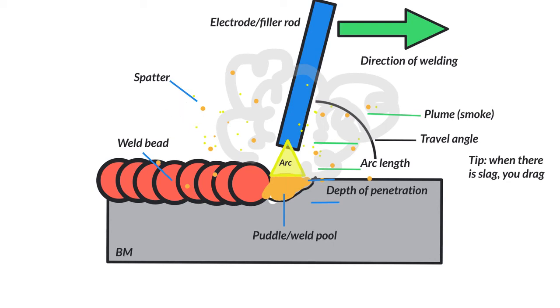We usually get spatter in about all major processes except for TIG. If you've got excessive spatter, we've got an issue — let's fix it. We don't want excessive spatter with MIG either. You can see the depth of penetration and how much we're burning into the base metal. Arc length should be about one rod diameter depending on the process. For TIG with an eighth-inch tungsten electrode, about an eighth inch off is fine, though running close is preferred. Same thing for stick — eighth-inch rod, about an eighth-inch distance. For flux core and MIG, arc length is based on voltage.